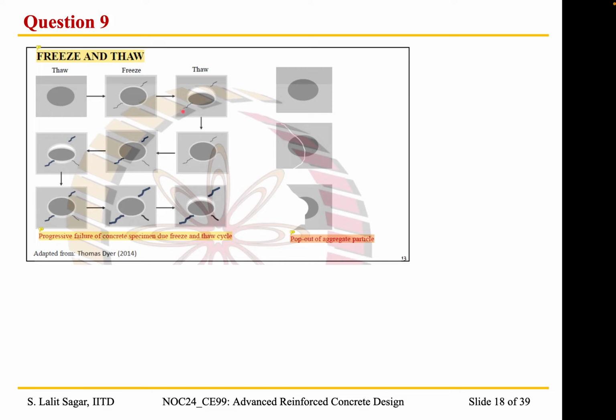As and when the water accumulation takes place, again freezing and thawing, it leads to the formation of wider cracks. However, if we take this aggregate particle, if the aggregate has some pores, as you can see here, whenever there is ingress of water, water tends to accumulate in the pore within the aggregate, and whenever there is freeze and thaw within the aggregate particle, the aggregate particle can rupture. So this phenomenon is called the popping out of aggregate particle.